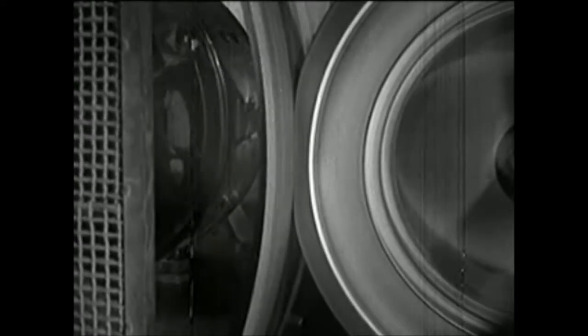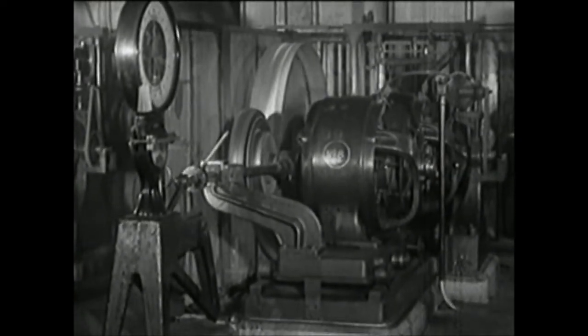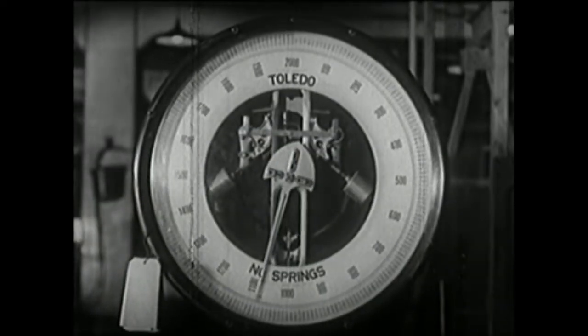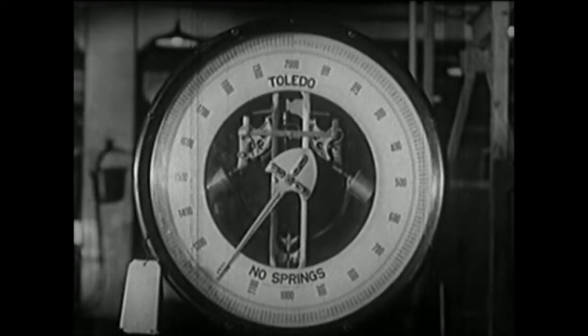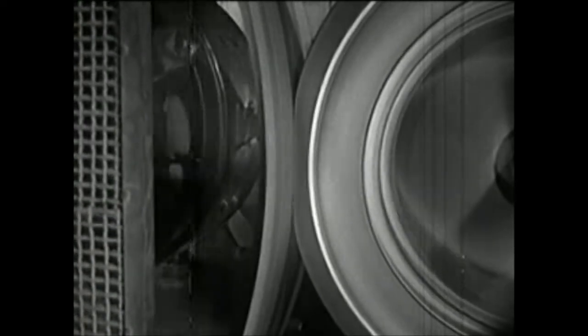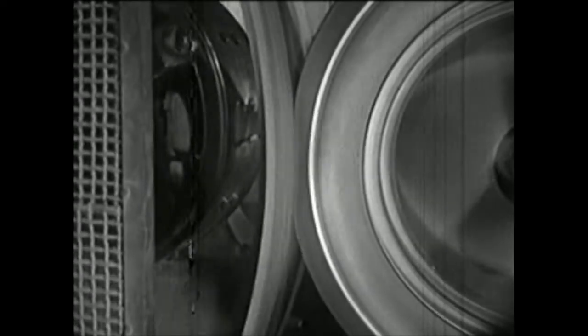Imagine the heat generated in the tires with an incessant pounding of the cleats, and every part of the tire pounding and flexing about 2,000 times a minute. The heat of the run expands the air inside the tire, forcing even greater pressure against the dynamometer wheel. Under these conditions, an ordinary tire soon fails. But the Brunswick Super Service, when put to this test, proves definitely its resistance to destructive high-speed flexing by running continuously for the equivalent of 10,000 miles without failure.